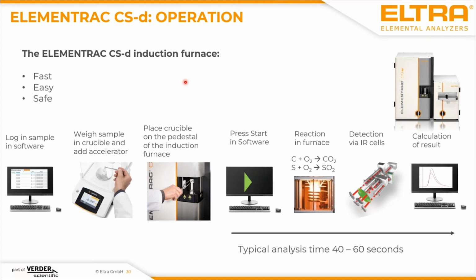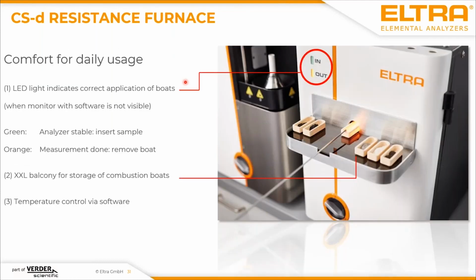The analysis time for the induction furnace is very short. It's 40 to 60 seconds. Yes, it's like in your kitchen. If you work with an induction furnace, induction oven, it's much quicker compared to the good old resistance furnace. And in the resistance furnace, you see it here, it's always on temperature. Induction furnace in between goes down to room temperature again. And in the resistance furnace, the sample comes in the hot furnace, and the sample is burned there, or CO2 is coming out there. And as I said before, the main difference is the lower temperature. But also here, everything is controlled via software.